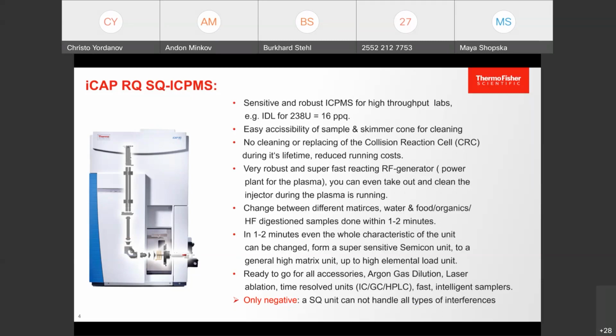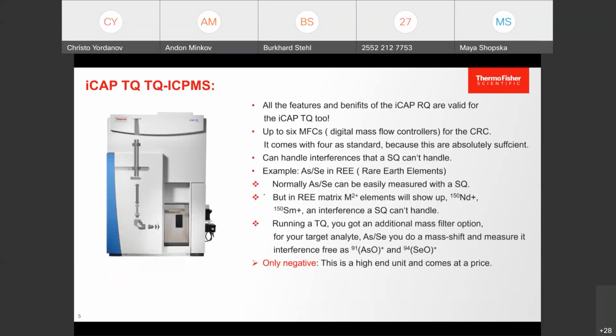I would say 95% of all possible interferences can be done with a single quad, but there are 5% left, and for this 5%, you need a triple quad. You face sometimes, especially when it's about geochem and rare earth elements, doubly charged interferences where you have to have an additional filter, so a triple quad. The first quadrupole acts as an additional mass filter, and then you measure your target element, your element of interest, by a mass shift, so that you do not measure arsenic or selenium directly on mass, you measure it as selenium oxide or arsenic oxide. The only negative about this unit, it's a quite high-end unit and it comes at a price.